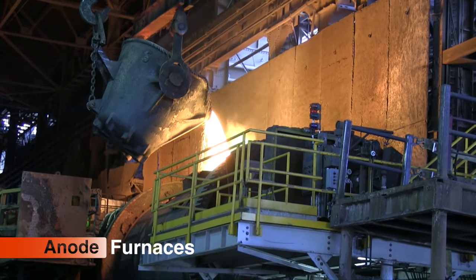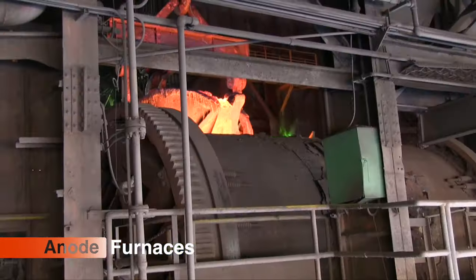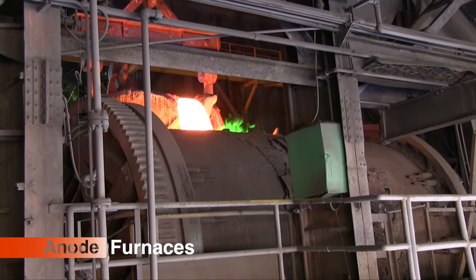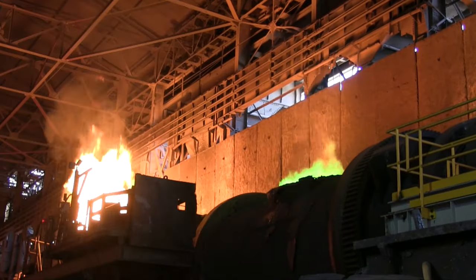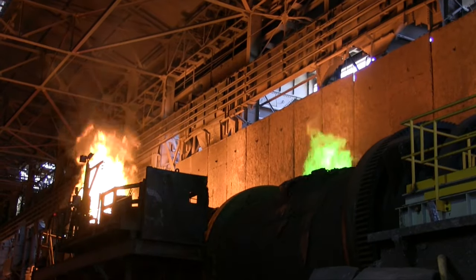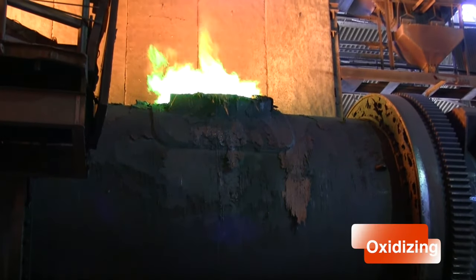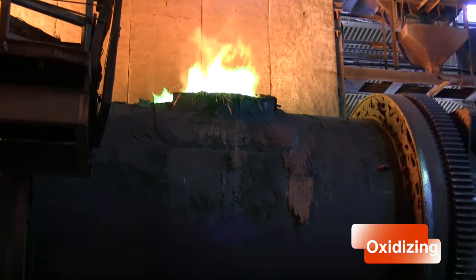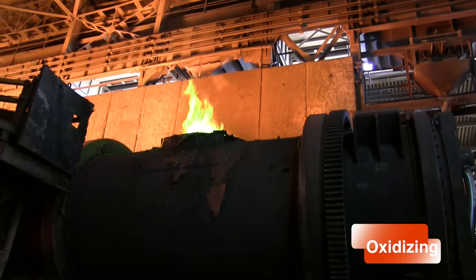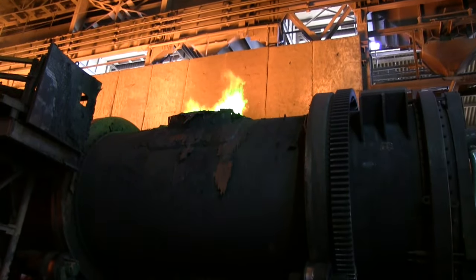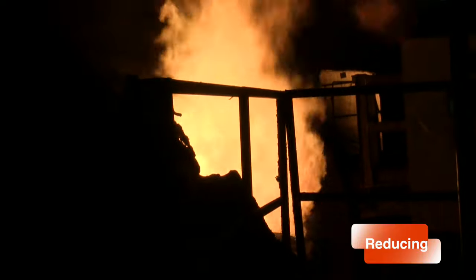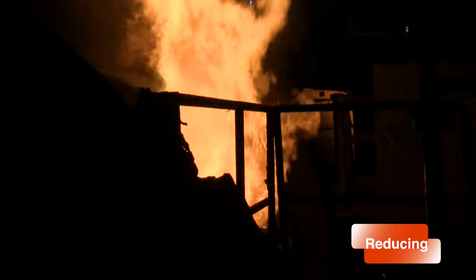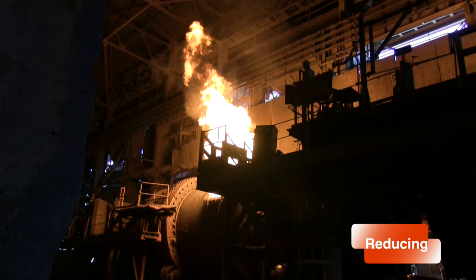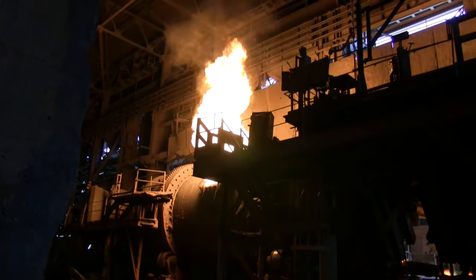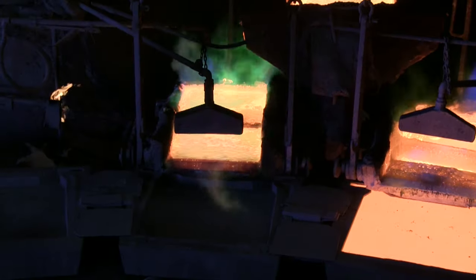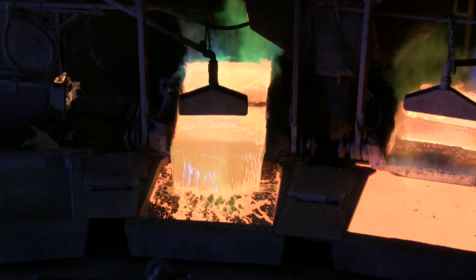Ladles send the molten blister copper to anode furnaces to remove the last remaining sulfur and oxygen using more blast air along with natural gas and steam. During oxidation, air blown into the molten copper removes the remaining sulfur, driving it off as sulfur dioxide gas. In the reducing stage, we use a combination of natural gas and steam to lower the oxygen content of the molten copper to acceptable levels. Oxidizing and reducing in the anode furnaces results in copper of 99.8% purity.